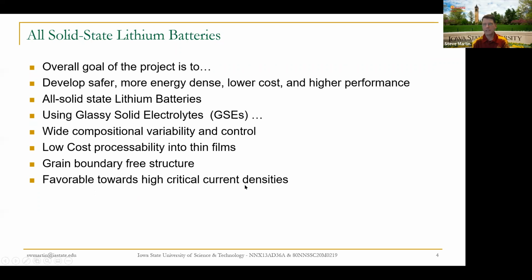A critical current density is that current of lithium ions, not electrons. Remember, the electrons are going in the exterior circuit through the car or the cell phone. It's the lithium ion current through the battery. You want that to be as high as possible because every lithium ion has to be matched by an electron. So the high conductivity, the high current allows high power from these batteries, and these grain boundary free glasses promote higher critical current densities before they fail. So it's another technical advantage of the glasses.